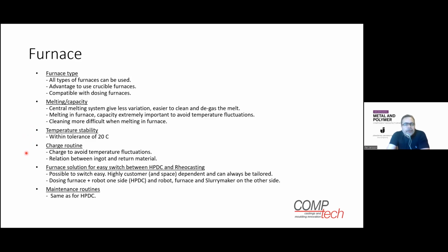If you melt at the furnace, we see that charging of the furnace is important. If you lift out, let's say for instance, 10 kilos in each shot, it's important that you add 10 kilos also. So you don't cast for 1 hour and then need to add the whole amount that you have taken out. That's bound to give you problems with temperature fluctuations. So that's something that needs to be considered if you have that system in place.